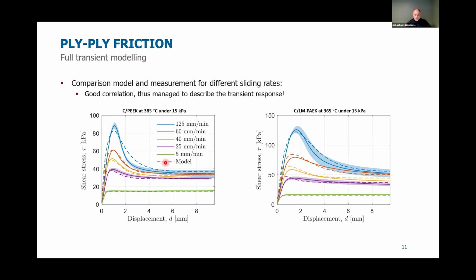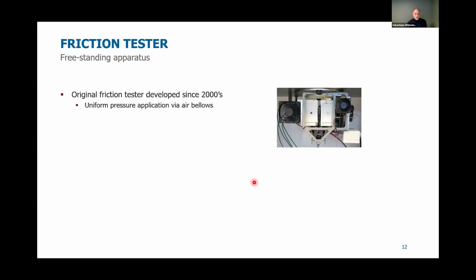So here, one model we could fit to varying rates, describing the full curve for different materials. So we took carbon PEEK and carbon low melting PAEK. So very happy with that result.